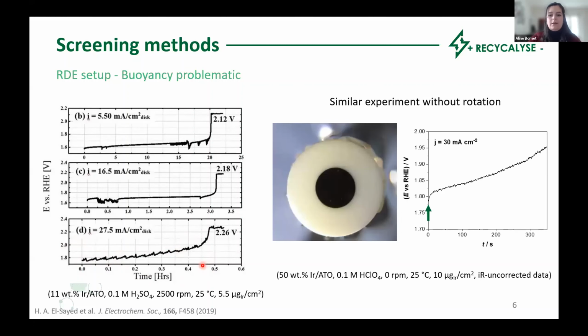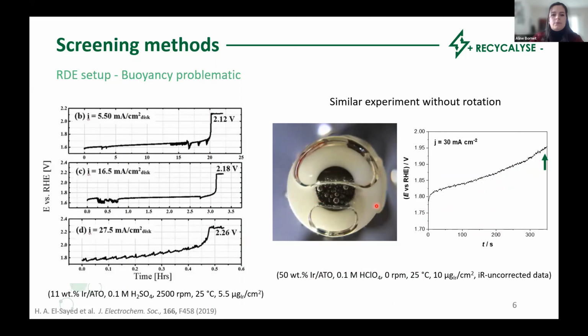We performed a similar experiment, however, without rotation, to emphasize the massive accumulation of bubbles. And on the right graph, we can also observe this increase of potential over the time of the reaction. We also recorded a video where we can very nicely see the formation of the oxygen bubbles. The parts that are covered by bubbles, so here for instance, are no longer contributing to the reaction. This means that the uncovered parts here are more and more stressed, and that is why we see the increase of the potential. So definitely, this setup is not suitable for the oxygen evolution reaction.